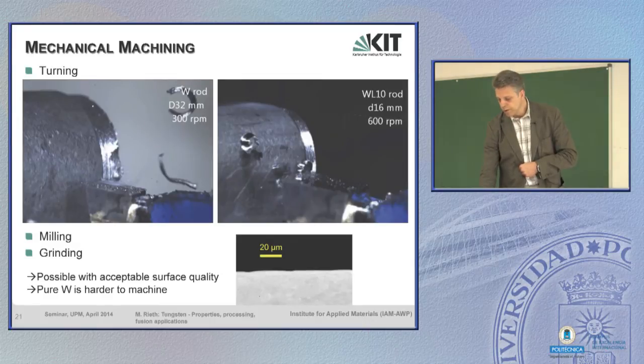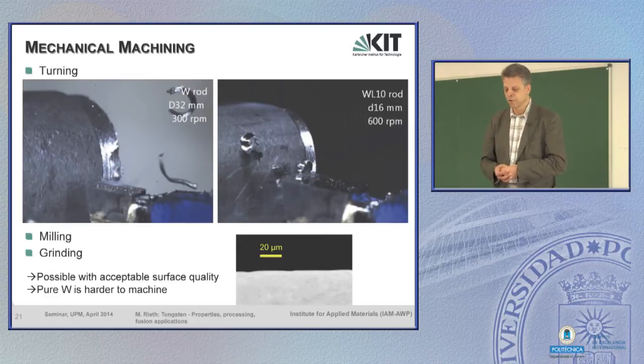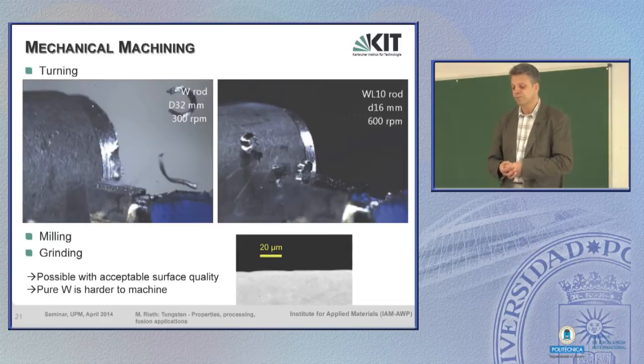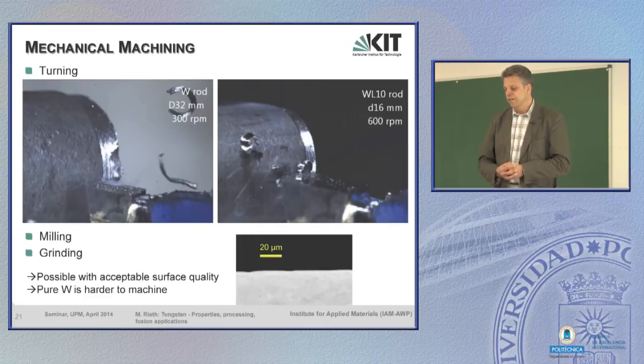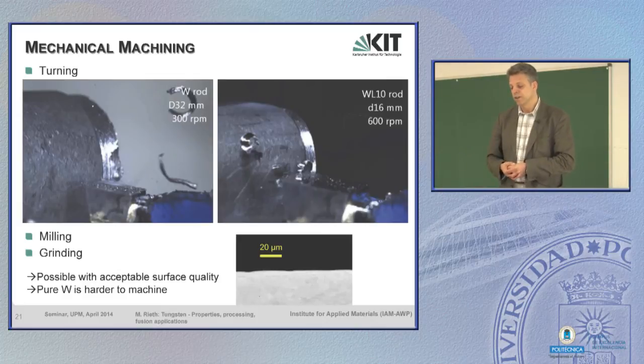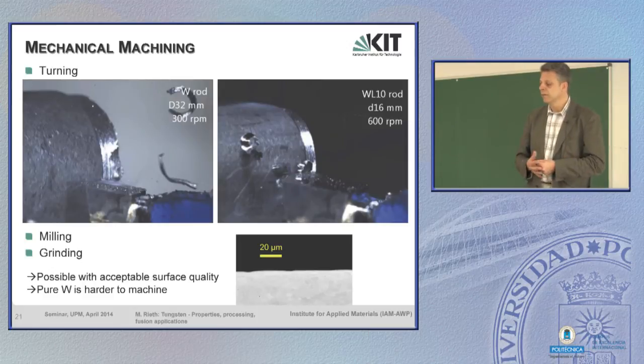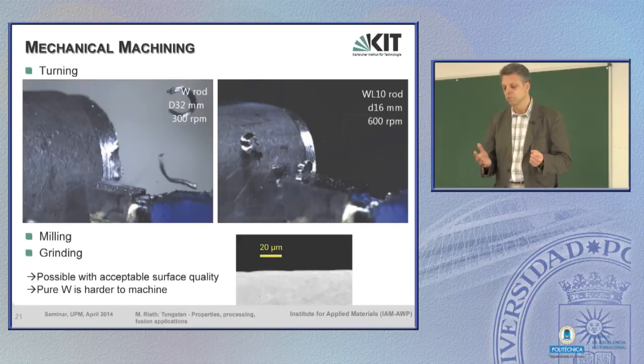if you see some turning experiments, it more or less behaves like any other metal you can turn, and maybe it's not so easily recognizable in these movies, but the pure tungsten is harder to machine, and the grain stabilized tungsten produces finer chips. The chipping behavior is more favorable. They are better to machine. The surface quality by this conventional machining is quite good, perfect, not to say. So milling, grinding, turning is not a problem.